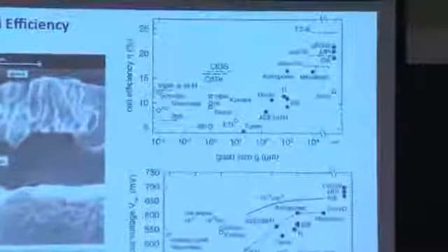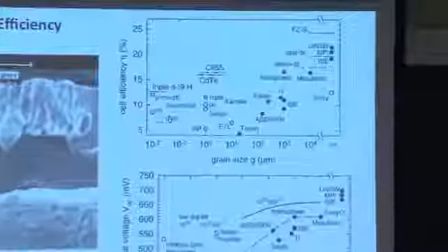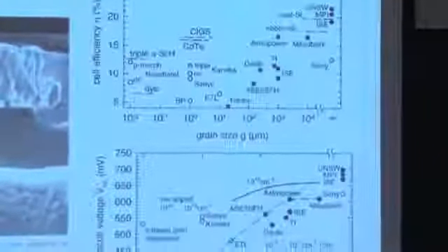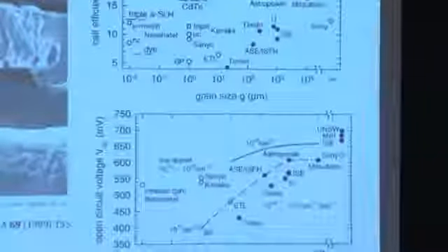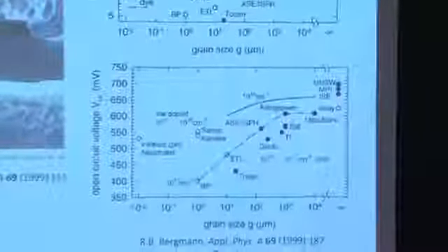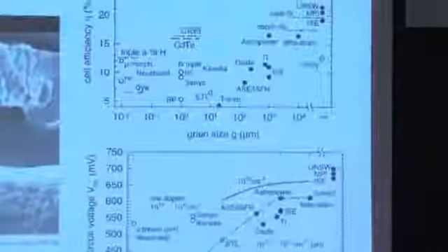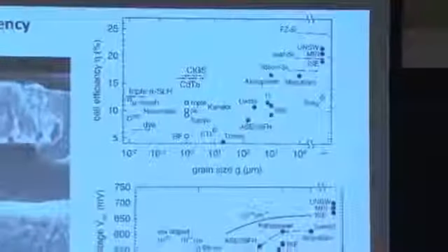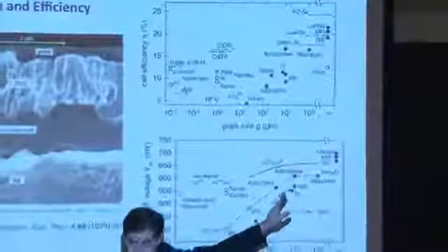So these are some very rough plots in crystalline silicon for thin film devices and for some thicker ones as well. Cell performance is a function of grain size. And I show crystalline silicon because the data is really well developed for it. But you see similar types of plots for organic materials, for some inorganic thin film materials like CIGS and so forth. And this convolutes a few different parameters. You have to take into account that the recombination activity of the grain boundary is also a factor.